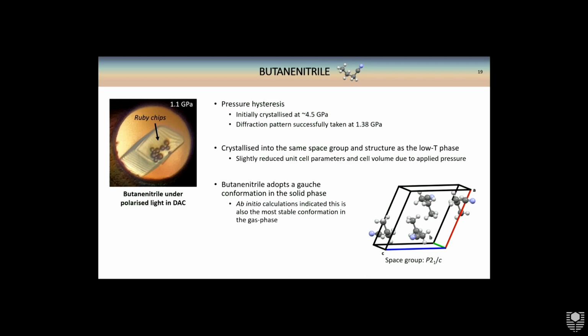And for butanenitrile, we found it actually crystallized into the same space group and structure as the low temperature phase, as is shown over here, although with a slightly reduced unit cell and volume due to the applied pressure. Butanenitrile, in general, adopts this gauche conformation in the solid phase, and we did some ab initio calculations which indicated this is also the most stable conformation in the gas phase. So the low temperature or the high pressure structure aren't forcing the molecule into a position that it doesn't want to go into.